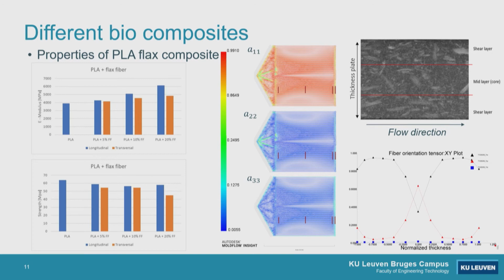Okay, so just some properties of this short fiber reinforced PLA materials. So if we go for the neat PLA modulus of 4 gigapascal, so if we go for 5% and up to 20%, of course, we see some differences, longitudinal and transverse direction. So also there, we see some improvement of mechanical properties, but not as you would expect from the theoretical situation. So also due to some yet unknown behavior, let's say, within this flax fiber or interfaces. If we go for the strength, then we see it's getting down. So that's of course not that nice, but we have to choose, of course, depending on the application. Do we want to have a kind of increase in stiffness, or what's the main request from the application?